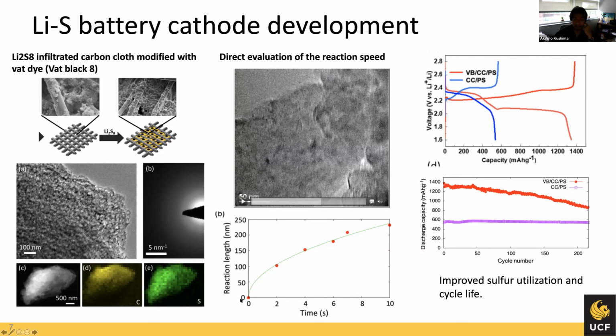You can also measure the reaction rate. You will see that the reaction can take place really quickly if the size scale is within a couple hundred nanometers, but this is a diffusion-limited process. So if you increase the size up to micron scales, like 10 microns, then the reaction will take hours, about 10 hours. So having the nanoscale microstructure is very important in this kind of structure, and it confirms the performance of these materials, with very good improved capacity and also cycle lifetime compared to the one without this modification.